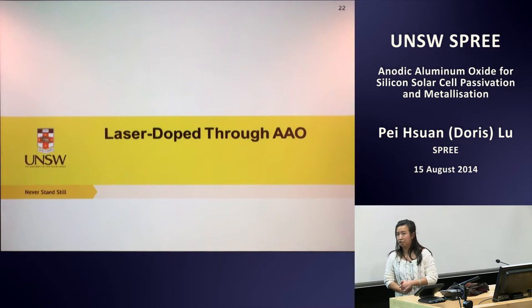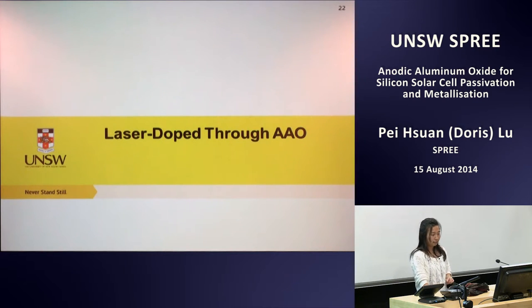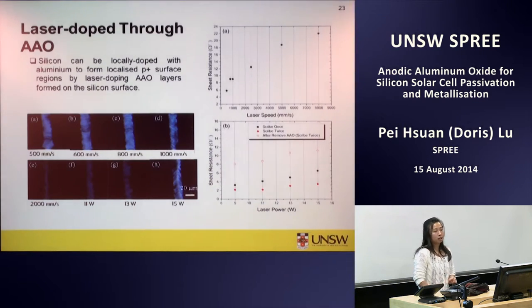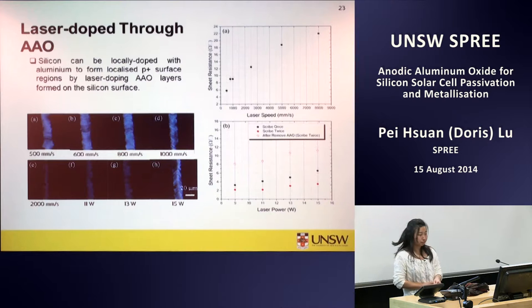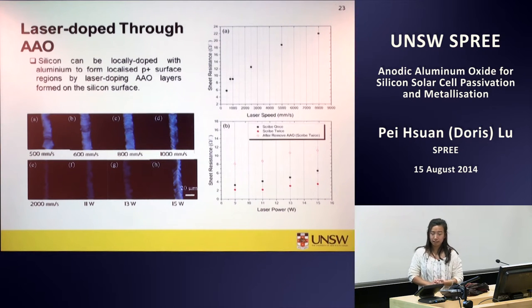This leads to research on laser doping through AAO, using aluminium within the anodic aluminium oxide as a dopant. At the beginning, when I played around with the laser speed, I achieved the lowest sheet resistance, around 6 ohm per square, at 500 millimeter per second. By further varying the power and the number of scans, the lowest sheet resistance of 2 ohm per square can be achieved at 9 watt